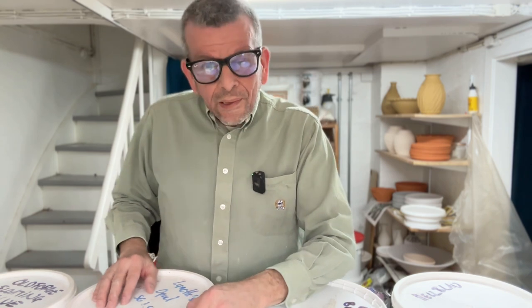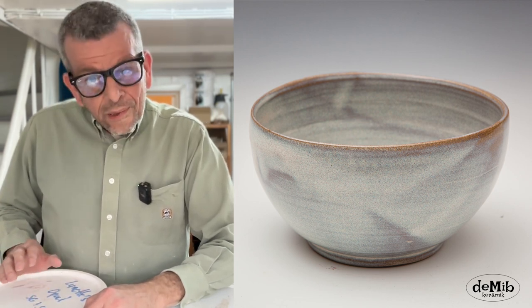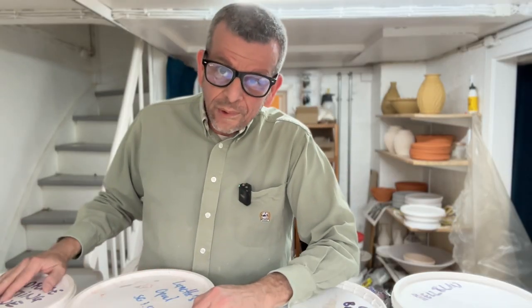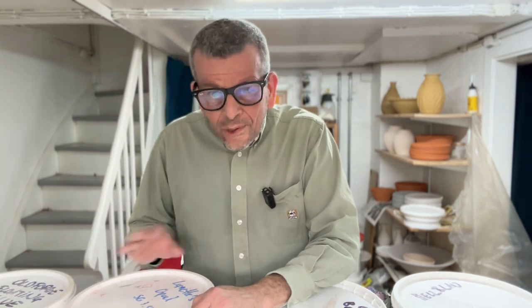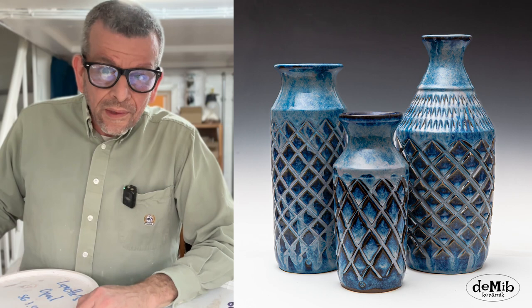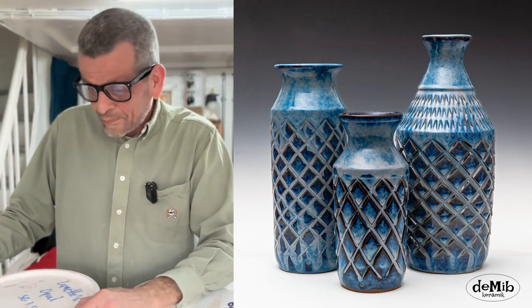Then I'm going to do Lineage Opal, which is sort of white. It's a very good glaze on top of Floating Blue, which I'm also going to use. But it also looks really good on its own — especially if applied very thin, then it becomes bluish. And of course, the other one of my all-time favorites: Floating Blue. There are a lot of different variations of Floating Blue. This one is largely based on Old Ford's version, where red iron oxide has been exchanged for manganese and a few more modifications, so it breaks in a more purple way instead of brown.